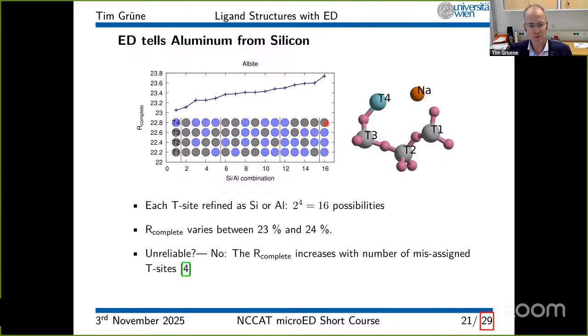So this is totally wrong, but the difference is only small. Remember, aluminum and silicon differ only by a single electron, which is not a lot. And on the left-hand side, it's the correct structure. So T4 was modeled as aluminum and silicon was modeled as a silicon. Now, when you plot the 16 different possibilities with growing R value, it turns out that the correct structure has the lowest R value and the incorrect one has the highest R value. And actually, it's growing incrementally the worse the model gets.